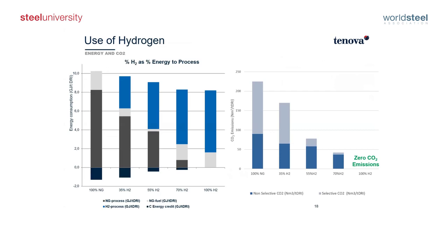And of course, the impact of the replacement of the natural gas with hydrogen is dramatic. One can reduce the emissions already by five times operating with 70% hydrogen in the feed. And of course, the CO2 goes down to zero when operating with 100% hydrogen. The division in our graphs between selective and non-selective is the CO2 that is caught by the amine scrubber in the cycle, and the CO2 that is caused by the process gas heater if the process gas heater is fired by natural gas.